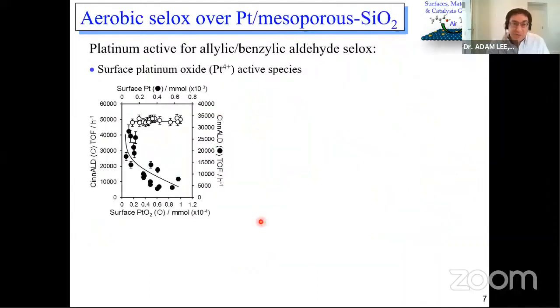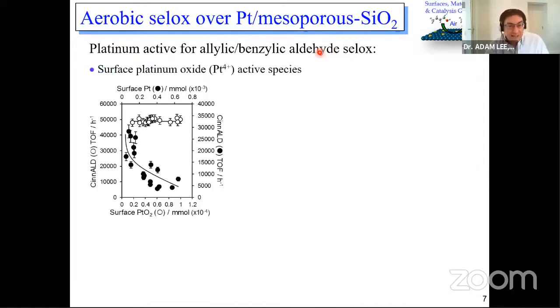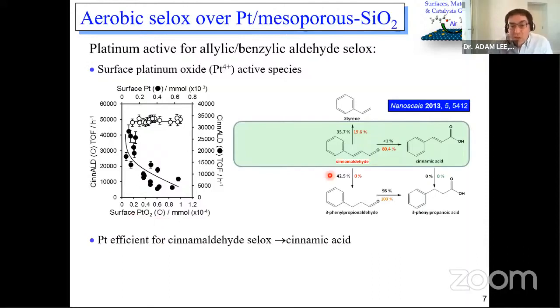However, it turns out that platinum is very active for aldehyde oxidations, step 2. So we've done a lot of work again trying to identify the active site responsible. It turns out it's also a metal oxide. So PtO2 is very good at aldehyde oxidations, just showing this here. So if you give a platinum catalyst aldehyde, it converts it very effectively through to the corresponding acid. So this is a selective oxidation, taking the aldehyde group to a carboxylic acid, and it doesn't touch the double bond. So platinum is great for step 2 of a cascade reaction.